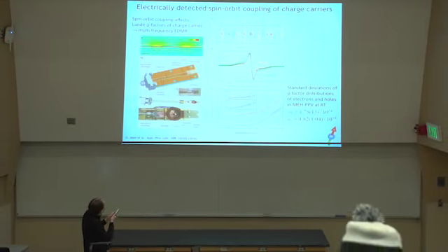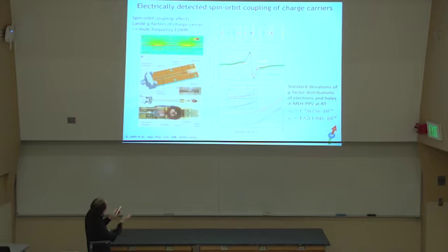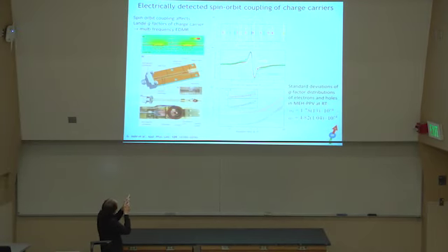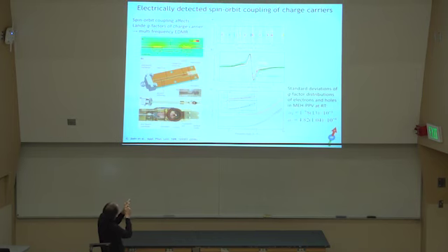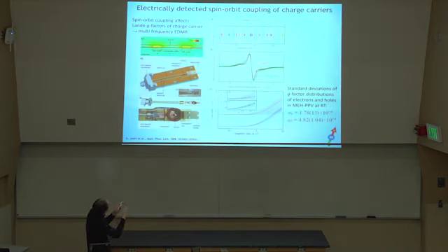So here's essentially that, that's a lambda over 4, and we put our samples on top. You see a simulation here. You only get good excitation fields, and we really did this for an OLED with a contact layer, which also messes with our magnetic field. That's a simulation. You need to be within a few tenths of micrometers in order to have reasonable fields. But then you get reasonable excitation fields. And again, that's lambda over 4, and you can take higher harmonics.